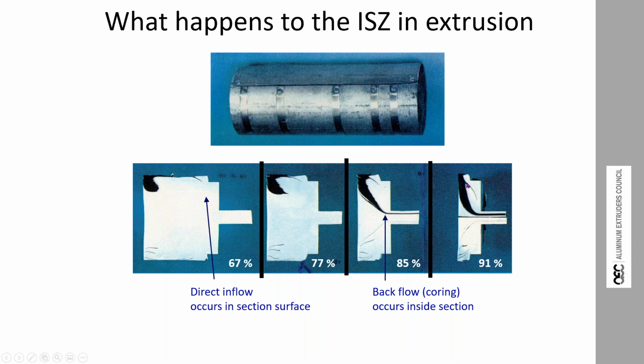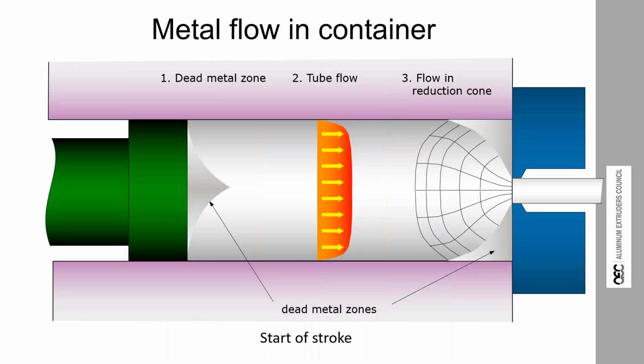And as we get down to a 10% butt, now you can see if we had a cavity up here on a multi-cavity die, that would be in the surface of our material. Inverse segregation zone would be there. And when it's anodized, it will come out a different color. And we will be making scrap. So this inverse segregation zone and the way it flows is very important. And a key part of it is controlling the container temperature.